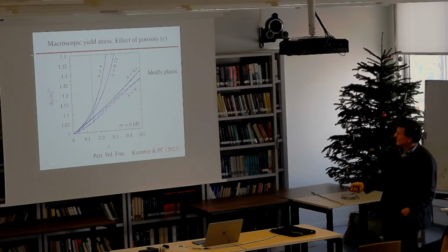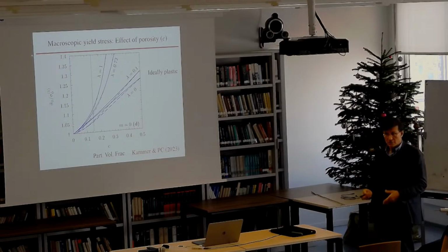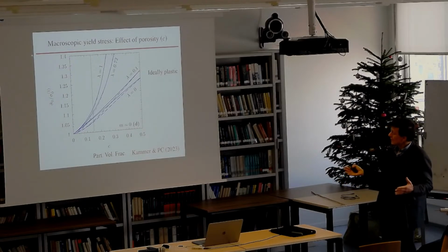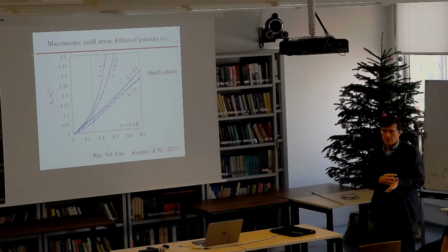These are some plots of the effective flow stress as a function of volume fraction. You have two lines here that correspond to pure shear and simple shear—pure shear is on top, simple shear is below, at different values of lambda. For large volume fractions near percolation, there's no difference between pure shear and simple shear.